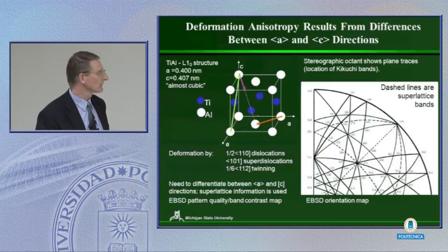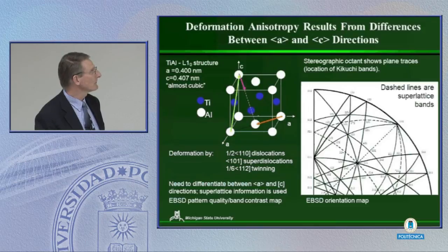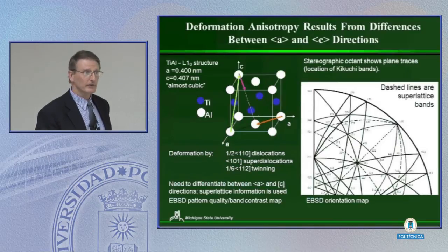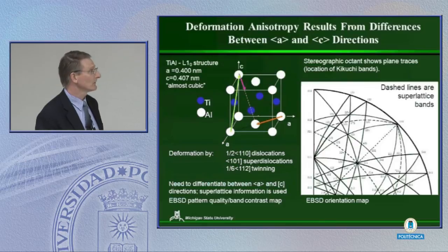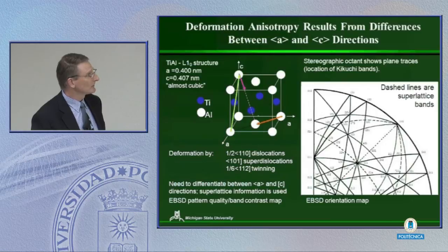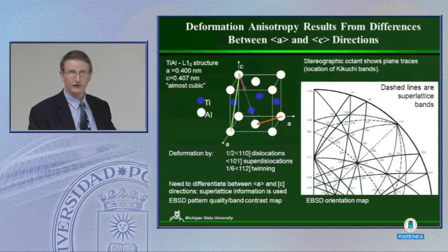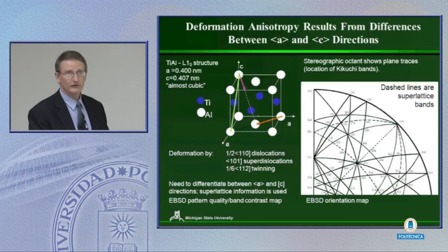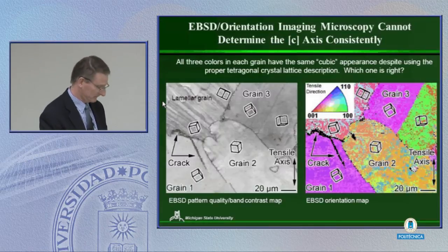and one thing that EBSD struggles with, is because the c/a ratio is very close to one here. EBSD has a hard time distinguishing between the c direction and the a direction. But this leads to a large anisotropy in the plastic behavior, so we really need to know the difference between those two. And we can do that by identifying where these superlattice bands are, which I've shown on this quadrant of a stereographic projection. So instead of having to deal with a simple stereographic triangle, which we would have to in FCC, we really have to worry about a much larger portion of the stereographic projection to give us all the information there.